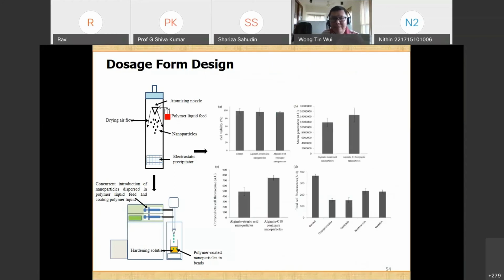Now, you can see in this slide, the nanoparticle that we prepare has a very low level of cytotoxicity. It can actually transport across the mucus barriers and be trapped by the intestinal mucosa prior to entering into the bloodstream to exert the anti-diabetic action. So the uptake of our nanoparticles by intestinal mucosa is mediated by caveolae and clathrin endocytic pathways.